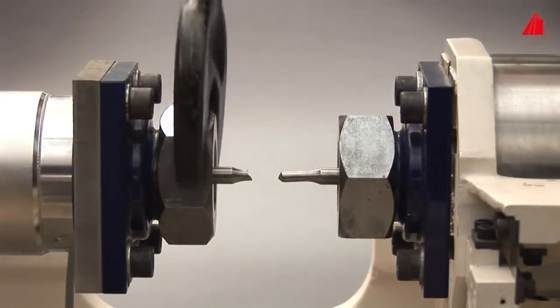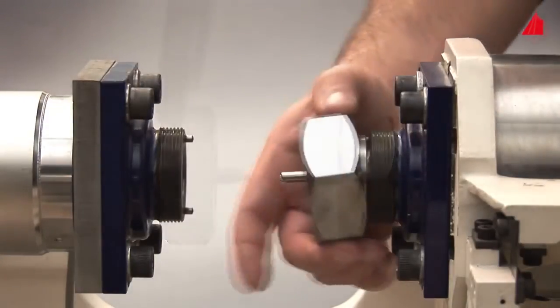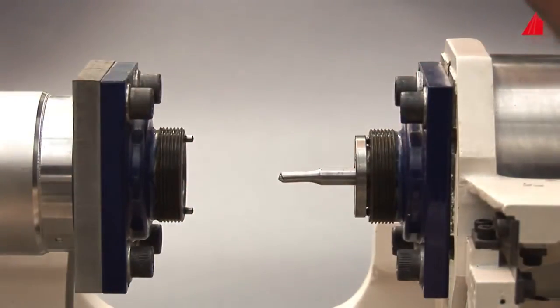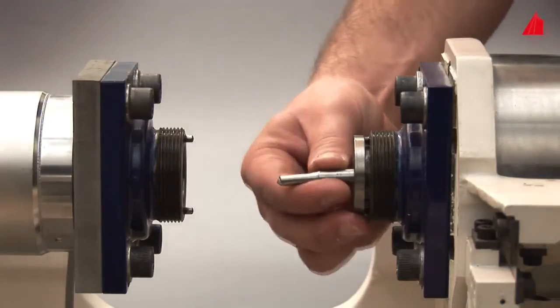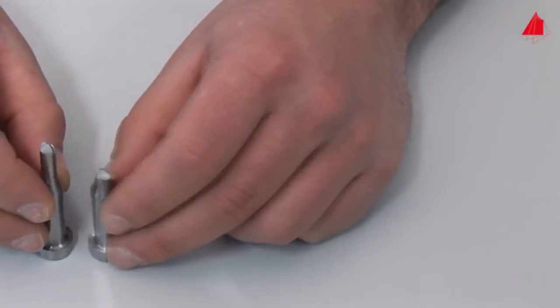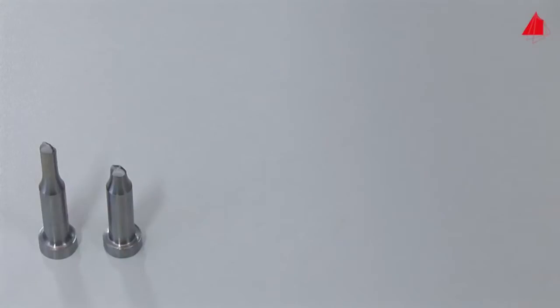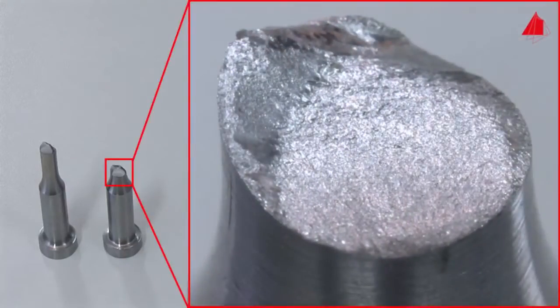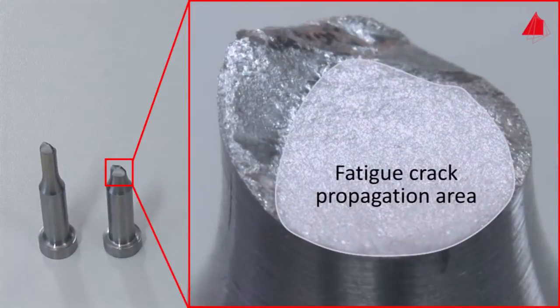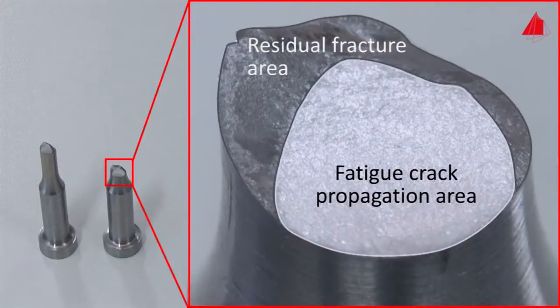The material tester removes the fragments cautiously and inspects the fracture surfaces. At first glance, the fracture surface looks unimpressive. A closer look reveals two regions: the rather dull, predominantly flat fatigue crack propagation area and the rough residual fracture area. The residual fracture area results from the final catastrophic rupture. The fatigue crack propagation area has developed during the cyclic growth of the fatigue cracks, starting at the surface of